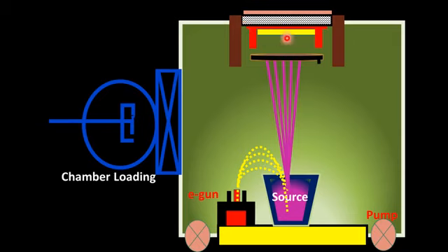Usually, dear student, please note that the heater used in an MBE system heats the substrate to somewhere around 200 degrees centigrade, whereas the source material usually has a temperature around 800 degrees centigrade.